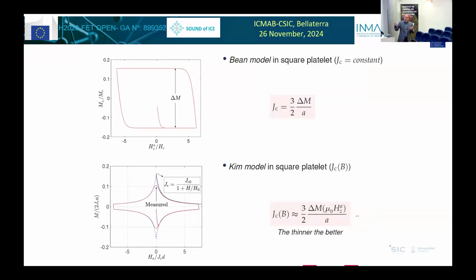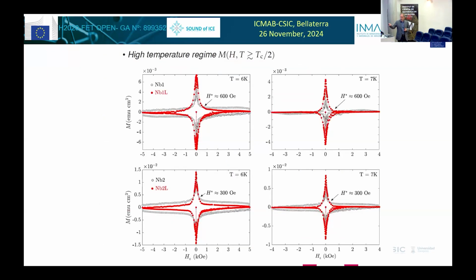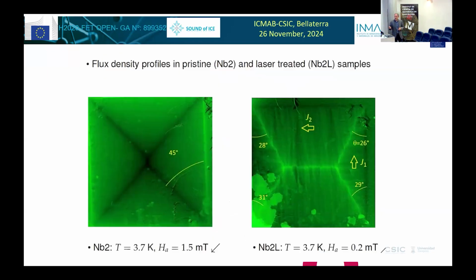So, okay, we use a number of models, the Bean classical critical state model for superconductors to relate the JC with the field. And this is a Kim model, which is a modification of this, which is more interesting for films. But I'm not going to spend time on this. Essentially, I show you the difference between the pristine niobium, original niobium, and how the field penetrates, and this is after we made the nanostructure.